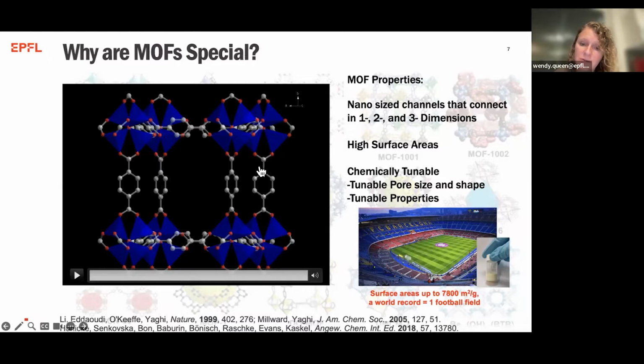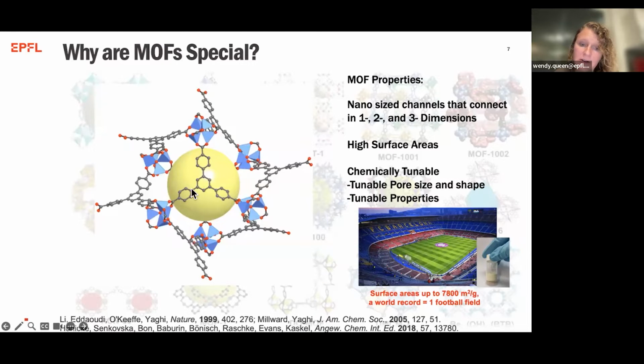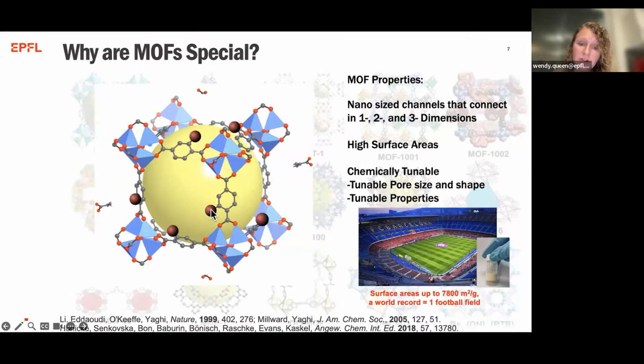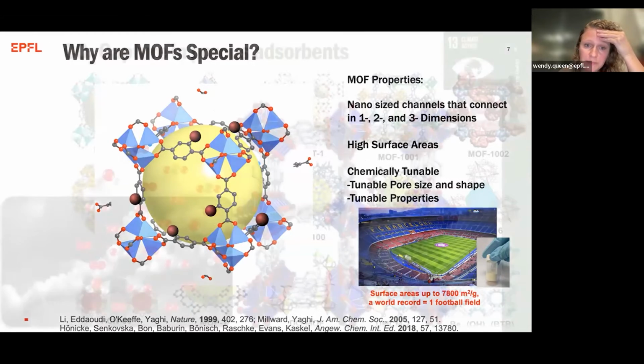As mentioned, they're highly tunable, and this is interesting. For instance, you can go from this linear link now to this trigonal link to allow you to tune the pore shape and the pore size. You can imagine you could also elongate these links to tune the pore size. In addition, you can functionalize the surface of your organics, and this will allow you to tune how your material interacts with incoming guest species, and for instance, boost both our capacities, how much we can absorb, and how selective our materials actually are.